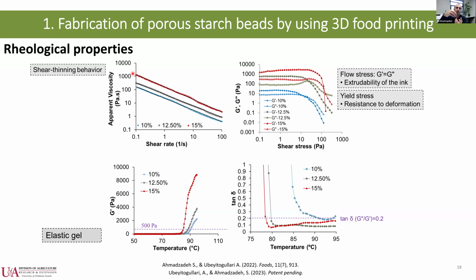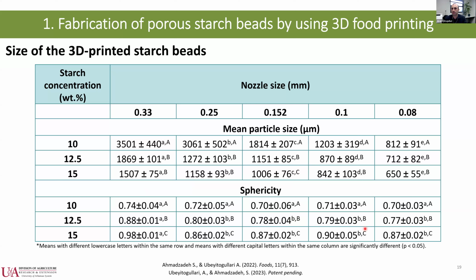So the pressure or the stress at the nozzle is higher than the regular material you have. So as you push it through, you are applying more force, and as you apply more force, you want your viscosity to go down so that it's easier to extrude. But another thing that we will discuss in the next few slides is how it bounces back, which is the recovery part. But that's one thing we look into: shear thinning behavior. We also look into storage and loss moduli to see yield stress and compare those. Tangent delta here, we look into that to see how the gel behaves. And in this case, we have an elastic gel that can support 3D printing.